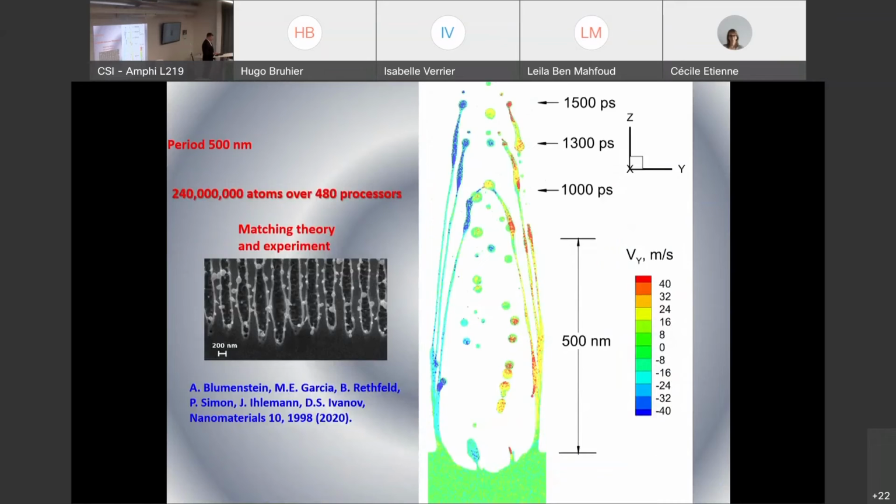So now we can understand why we have merging walls of the nanostructures, periodic nanostructures at high fluence. If you now plot the field of velocities in tangential component, so it's velocity in y direction, color means velocity, we can see that the left walls move to the left and right walls move to the right. So that's the reason that if the structure opens to the air, it can most likely merge with the neighboring walls of growing structures.